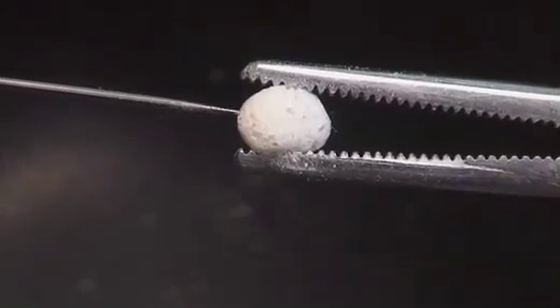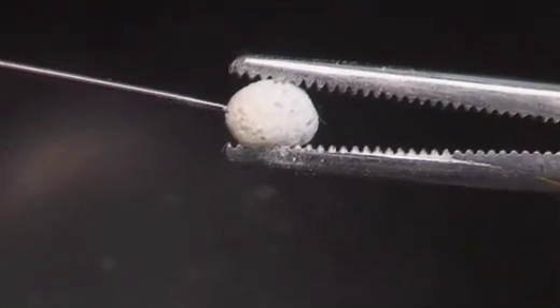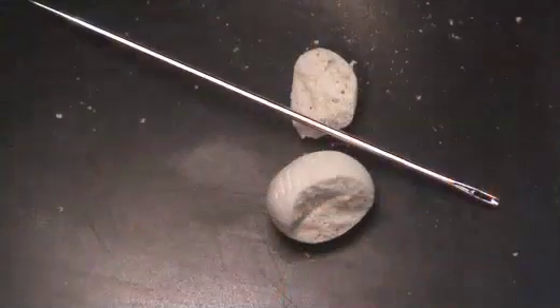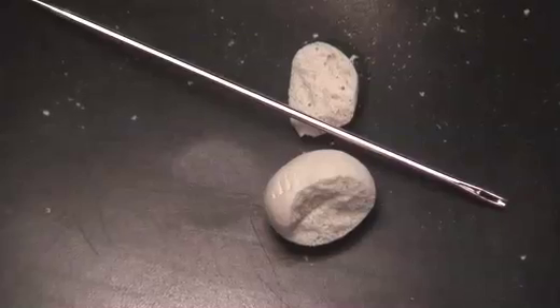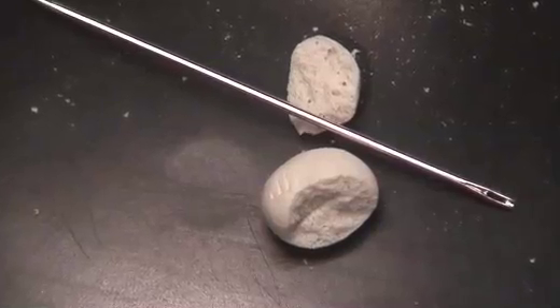The beautiful part about Poraver, and this is the biggest secret of Poraver, is we have a very high compressive strength of Poraver. But if you look at the surface compressive strength, it's very weak. So basically you can take a pin and you can easily go through the Poraver bead, and that is one of its main attributes for ASR, which is alkali-silica reaction. When gelling occurs, the gel actually wants to move in the direction of least path of resistance. So instead of going back into the cement and expanding it, it'll actually puncture the Poraver bead, enter it, and over time it'll neutralize, which means there will be no more silica-alkali reaction.